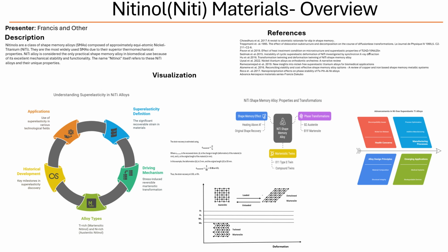Can you elaborate on that? How does that work? Well, imagine you have two materials that are trying to fit together, but they have slightly different shapes. That mismatch is going to create stress at the interface. And in SMAs, that stress can be enough to trigger slip in the austenite, even if you're not applying a large external force. What's more, this transformation-induced plasticity can actually train the material over repeated cycles of transformation. What I mean by that is the material might start to develop a kind of memory for a particular deformation path, making it more likely to deform in that way in the future. So the transformation process can leave a lasting impact on the material's structure.